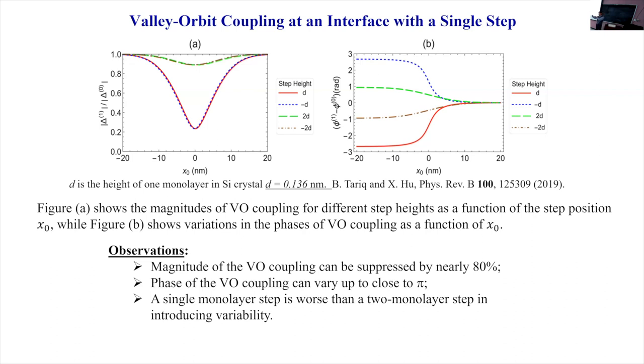So the quantum dot mostly sits on the terrace or actually sits on the step, right? We can see how, as we move the step within the quantum dot, the valley orbit coupling changes. What we found was that the valley orbit coupling magnitude can change pretty dramatically from, let's say, 1 down to maybe 0.3, so a 70% reduction when the step sits in the middle of the dot. And the valley orbit phase could switch by quite a large value, from close to pi all the way to roughly 0. So you can have an almost pi phase change in the valley orbit coupling.